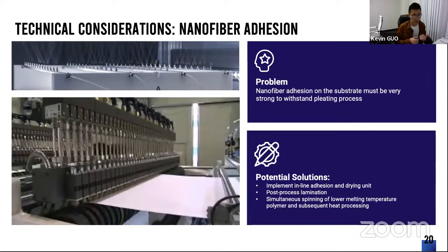The first one: we can apply a glue layer before the electrospinning process in order to increase the adhesion. Second, we can also laminate another protecting layer on top of the nanofiber to maintain the integrity. Third, we can also simultaneously spin another lower melting temperature polymer combined with the current polymer, and later apply a heating process so the lower melting polymer becomes the glue to enhance the adhesion.